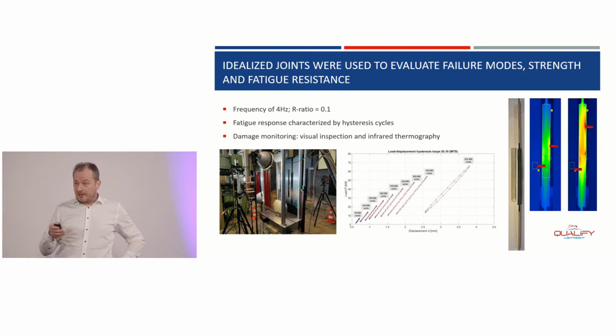And then, for example, at the right, you see an image of the damage evolution taken by 2 infrared thermographic images. At the left one with a lot of green at the start. At the right, very close to the failure, where you see a little bit of hot spots arising at the interface between adhesive and composite.